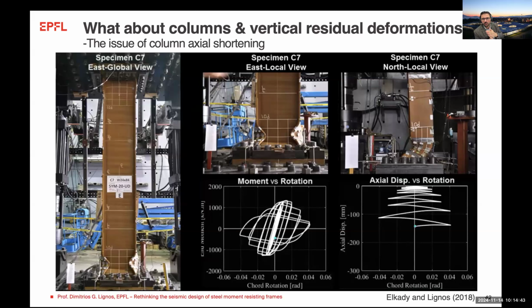So if we talk about finite element or OpenSees, essentially the way we treat this problem is that you have to consider a constitutive law that is calibrated properly, and I showed you how. Then you have to consider imperfections in your finite element model so that you can trigger buckling at the right time. And on that, again, we have provided pretty detailed studies into what the imperfection amplitude should be. In particular, we have shown that, for instance, if you are assigning imperfections in the range of d over 250, d being the web depth of your member, and bf over 250, which is the flange width of your member, then you can actually capture the onset of local buckling pretty well.